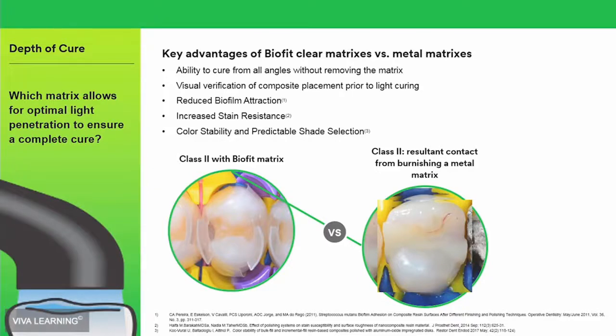And you also see those areas where there is flashing, where the composite is either leaking here or just broke off right here. So a lot of the researchers say, oh, David, the flashing is going to fall off. Well, only if it's accidental. So with the Clark Class 2, we're going to do a long radius bevel, then we sand it, we blast the tooth, and we'll show this study later. We're going to show 100 teeth at 10 years that have infinity edge margins and no mechanical retention, and they're not ditching, and it's not breaking away.